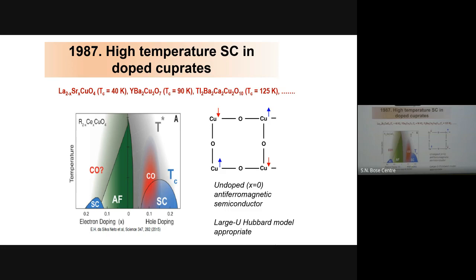And you dope it, meaning you put in a few strontiums. The antiferromagnetism disappears. There is a phase that no one understands, even after 30, 40 years. That's called the pseudogap state. Inside this, there is some CO, etc. Let me not go there, but you get superconductivity. On the electron-doped side, it stays antiferromagnet for a very long time. That's already a challenge, and superconductivity is over a very narrow concentration.